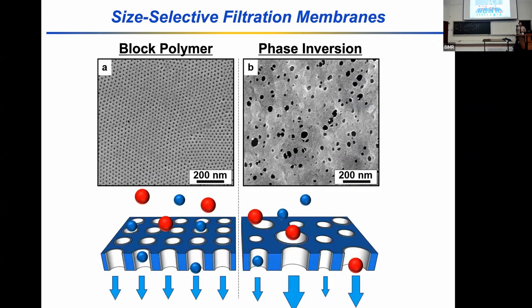But if I were to think about trying to make a better membrane, then what I would like to do is create a porous structure where I still have a whole bunch of pores, right? The phase inversion membranes, or the membranes made by phase separation techniques, do a nice job. They still have a whole bunch of pores in them, but they don't have a nice single well-defined size like the block polymer materials do. And so our first efforts as a research team were targeted at thinking about how to make membranes from self-assembled polymers. Can we use non-solvent induced phase separation techniques along with these self-assembled block polymer materials in order to create better filtration membranes?